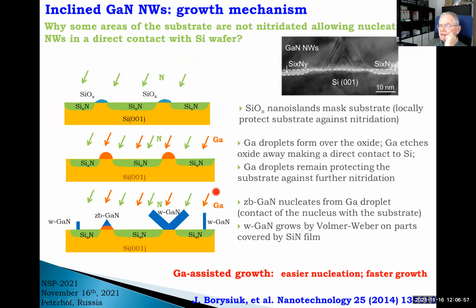Yeah, and then a piece of explanation of how it works in our opinion. Imagine that we have some silicon oxide islands left on the surface. Then we expose the surface to nitrogen flux just to induce nitridation, and these islands act as a mask. So this part is not nitridized. But actually, in the STEM image, you see that this is the zinc blende island, the first nuclei. Silicon nitride is here and here, while this part is not nitridized.